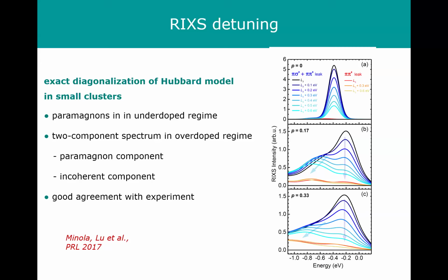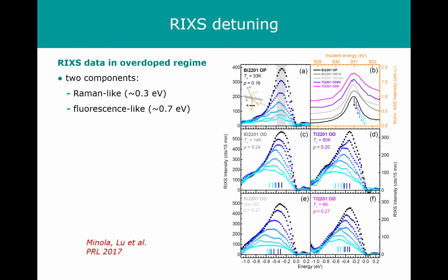And then we worked together with Yi Lu, who was a student of mine at the time, and he did some more calculations and found that actually both of these features are present, and their spectral weight changes as a function of doping. So at low doping, you see this Raman-like RIXS process, and the higher in doping you go, the more fluorescence-like the spectrum becomes, the more this collective magnon excitation disintegrates into particle hole excitations. And this is an effect that we actually found in two different systems, bismuth 2201 and the thallium-2201 system.